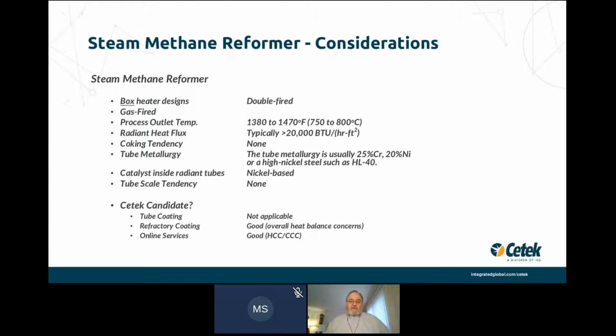So is this a good candidate for Cetek? Well, yes, it is, but we have to be careful. Tube coatings are not applicable because what we do with the tube coatings in refinery fired heaters is stop scale formation and growth. Since these are high alloy tubes, there's no scale formation, so there's really no point in coating the tubes. The oxide layer that forms on the surface of the tubes is a high emissivity oxide, so putting a high emissivity coating on is certainly not going to help anything other than cost our customers money, which is totally wasted.